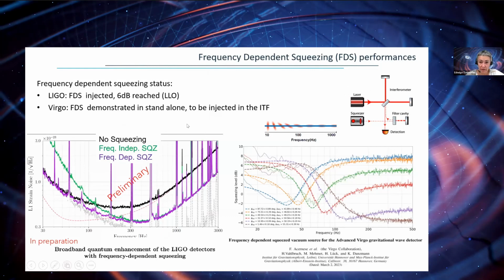Virgo and LIGO both managed to get this technique working. LIGO is a bit more advanced, as it has already injected the squeezing inside the interferometer, and you see here the result. In black is the sensitivity curve without any squeezing, in green is with the frequency independent squeezing, and in purple with frequency dependent squeezing.